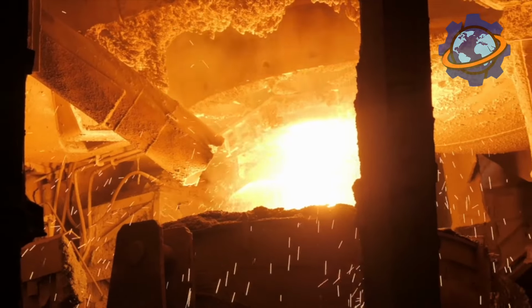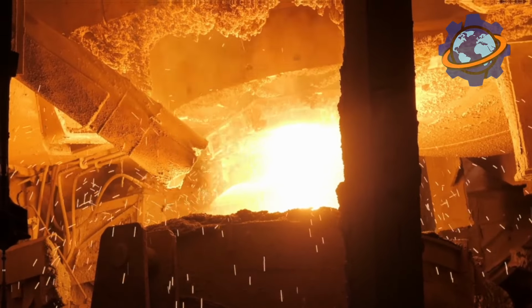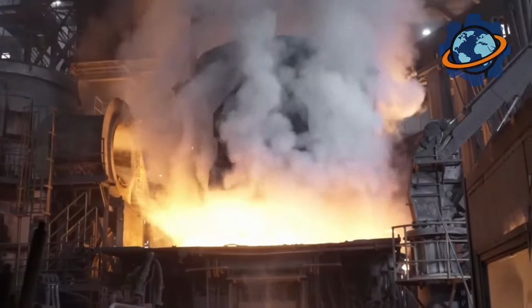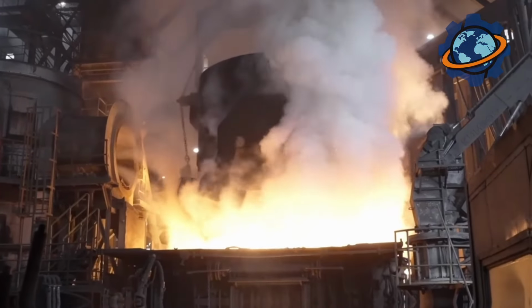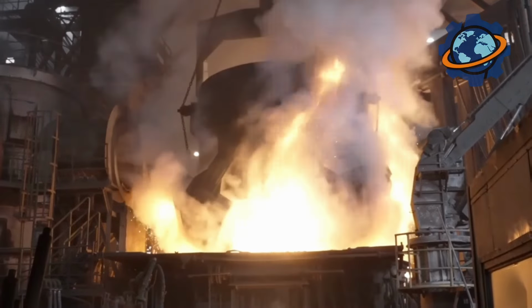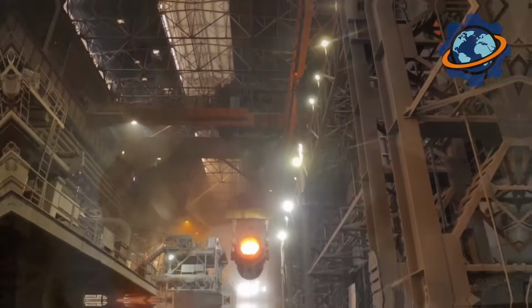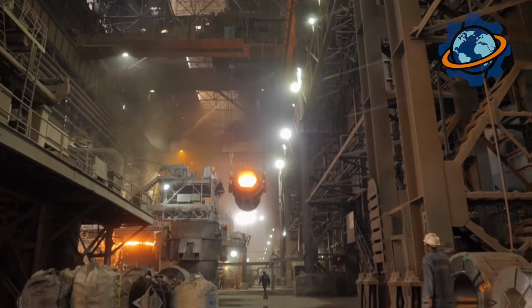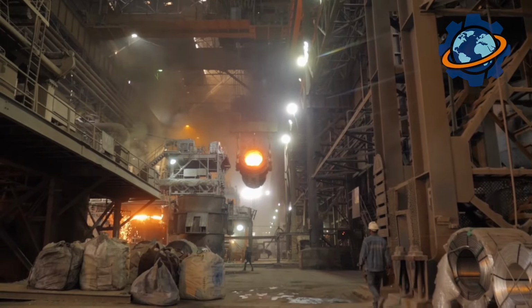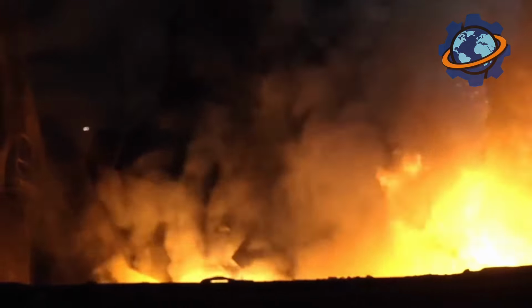The converter tilts, pig iron pours in, steel scrap is added for cooling. The converter returns to vertical position. An oxygen lance, a tube 20 inches in diameter, lowers from above. Oxygen flow begins. A jet of pure oxygen at 150 pounds per square inch pressure strikes the molten metal.